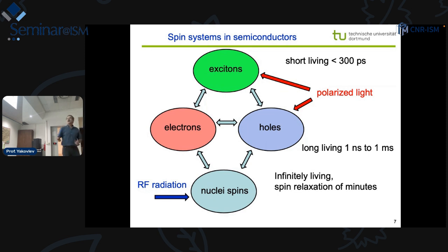But we also have spins in the nuclear spin system. In lead, for example, 20% of the lead has spin 1/2. This system is not addressable directly by light, but you can polarize it through the carriers, and you can read out its polarization through the carriers. One can also apply radio frequency under the conditions of magnetic resonance and erase the nuclear polarization, so you can learn what happens with the nuclear spin system. And the nuclear spin system is important for the spin relaxation processes of the carriers.